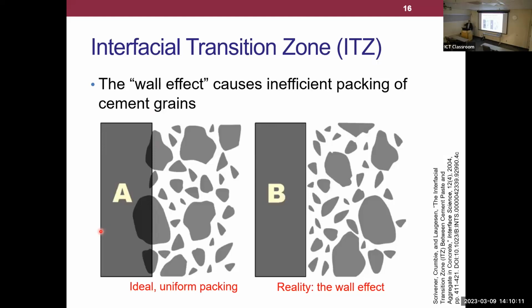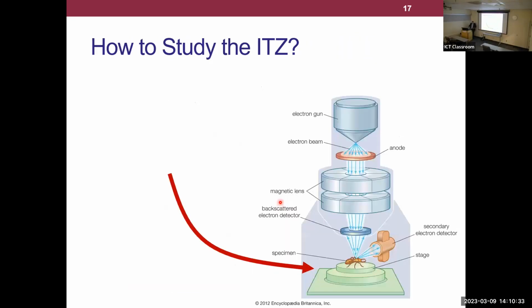So a 15 micron cement particle relative to a 25 millimeter coarse aggregate, that coarse aggregate is a gigantic wall. It basically means there's going to be inefficient packing immediately against that aggregate wall. Because of this inefficient packing, we form this thing known as the ITZ. So how do we study this ITZ? We're going to talk about what the properties of the ITZ are in just a minute.